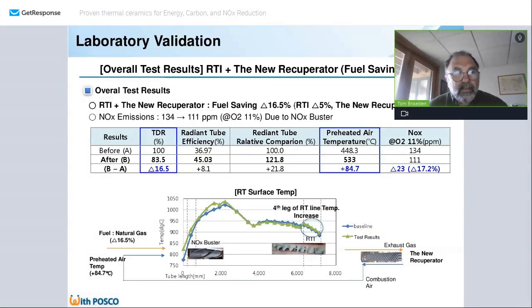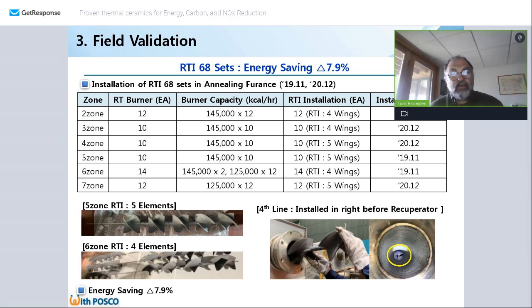And also then the increase in the radiant tube temperature, which allows more energy to be transferred into the furnace. The next step now was to go into the field. So they installed 68 sets of spiral core, the radiant tube inserts, into their annealing furnace. And from this field trial, they saw a 7.9% energy savings. So pretty unique. They saw about 5% in the laboratory and then 7.9% when they actually applied these into the field. And down here, you can see typical installation. They both tried 5 elements and 4 elements, and then the installation of the spiral core in the furnace.